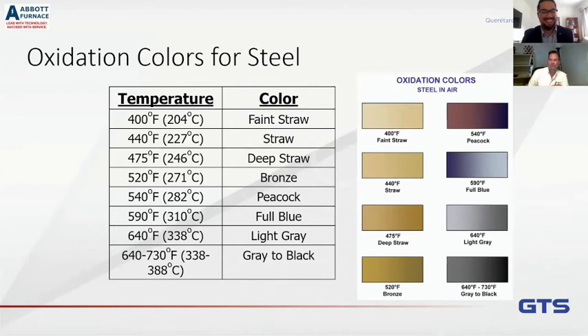Well, and by looking at the color, you can then tell exactly at what temperature it saw the oxygen source. So for instance, if you see a product that has this peacock color, similar to that gear that I showed you before, well, you know that that happened at about 282 degrees C, or about 540 degrees Fahrenheit. So now you can go back to your temperature profile and it'll tell you exactly where that happened in your furnace. Love it.